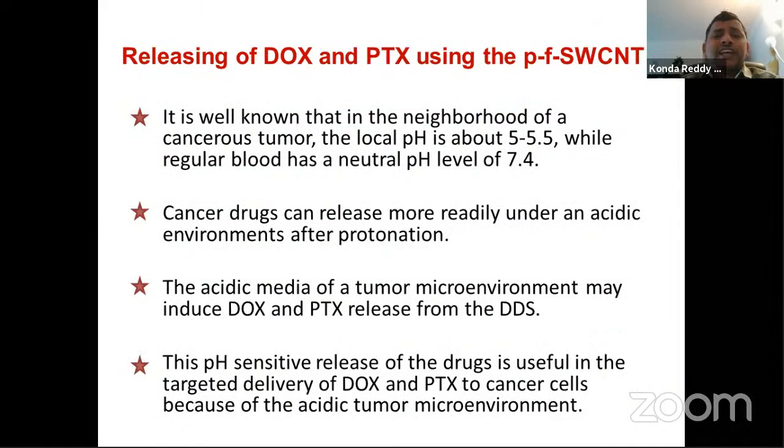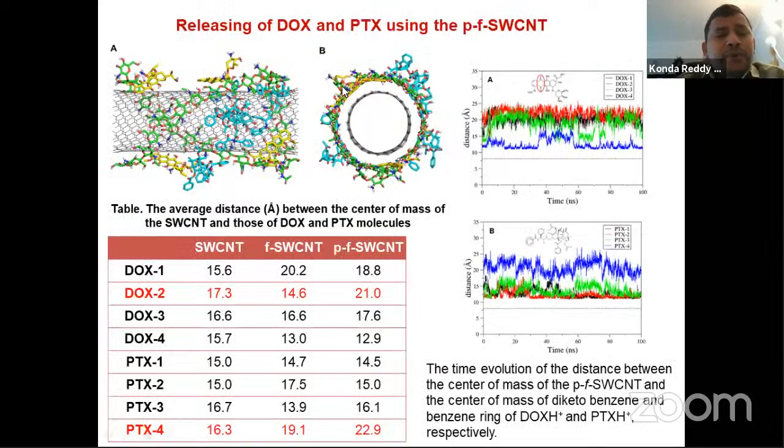Finally, we studied one of the more interesting aspects, which is the release of the drugs. There are many studies on co-loading, so what we did differently is this: we know that the cancer environment is highly acidic, so pH-sensitive release of the drugs is useful for targeted drug delivery. We protonated both the chitosan and the DOX and PTX molecules, because when the drug molecule or chitosan enters the cancer environment, there is a chance that they get protonated.